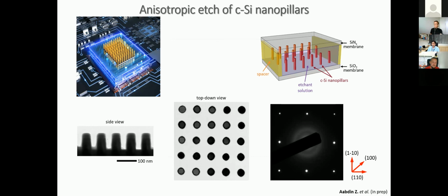Now instead of nitride membrane, we have an oxide membrane, and oxide is very fragile. So you have an oxide membrane here, and then you have silicon nanostructures here. And this is a crystalline silicon. You can see, look at the diffraction pattern. It's beautiful, right? So it's a single crystalline diffraction pattern.